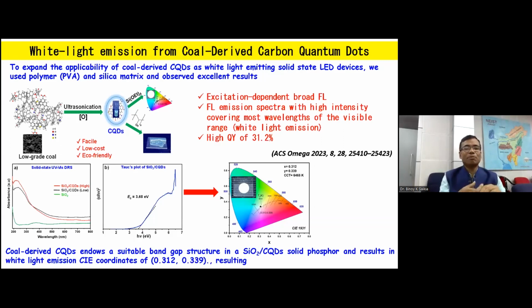In this case we have done an experiment, and I'm happy that it was published recently in the ACS Omega journal, in which we gave an organic polymer matrix, and we found that after applying the organic matrix, it simply gives a white light with a very high quantum yield, about 31%, and it lasts for several months. So it could be a very good lead and very good application, which makes it more applied research, giving an alternative utilization of such natural carbonaceous sources.